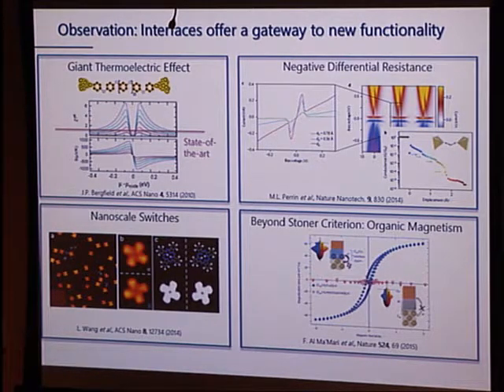That then is sort of a corollary. What that will tell you is that you can expect new phenomena to appear at the interface. And I'm just picking four here that I think are quite nice. If you take a molecule, a conjugated molecule, and sandwich it between two electrodes, and you then measure the thermovoltage or the thermoelectric efficiency, ZT. So that's sort of a figure of merit. And current champion materials are somewhere around 1.8, I think. If you do this right, you can get ZT of 6.